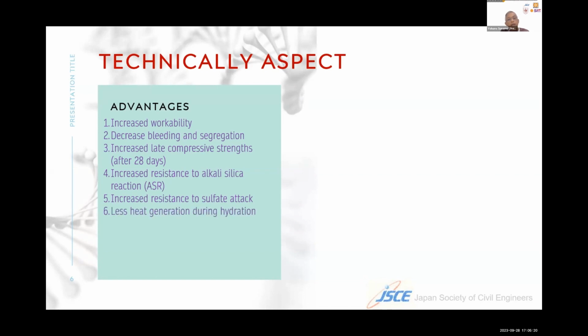Six, less heat generation during hydration. It's very helpful in mass pouring casting, where usually the thickness of the concrete is quite large. Sometimes 1 or 1.5 meters. So in this condition, if there is a temperature difference, it may cause cracking. So this can be a problem because in concrete, the hydration process increases the temperature of the concrete.